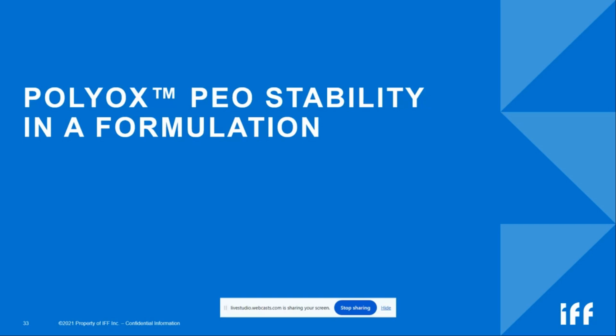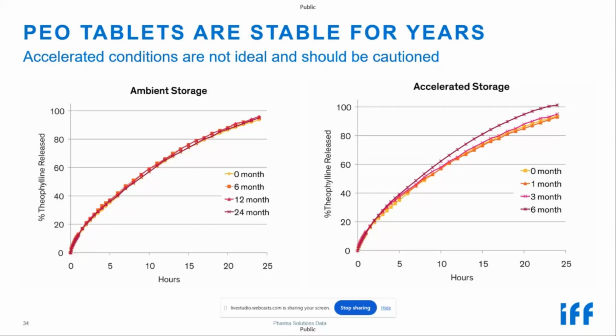A lot of times we get questions around, well, how does that translate to stability in a formulation? You have POLYOX, you compact it into a matrix, and you put it on stability. What happens? Well, we've tested this with a model formulation using theophylline, blended with coagulant, a high molecular weight of 5 million Daltons, some Avicel PH 102, and a low level of magnesium stearate, put on stability in ambient storage conditions for 0,